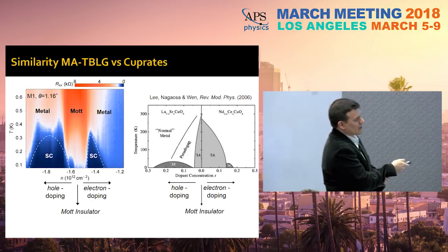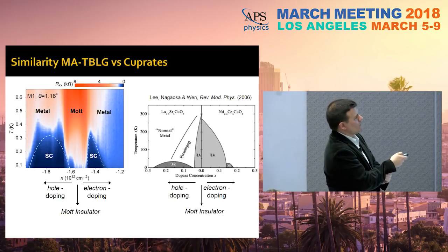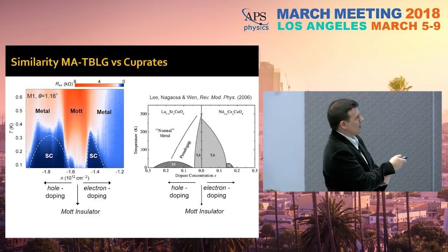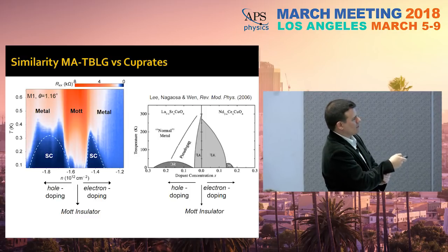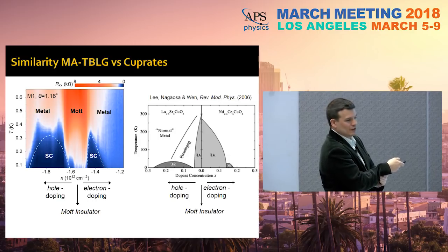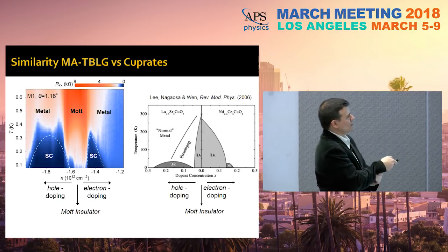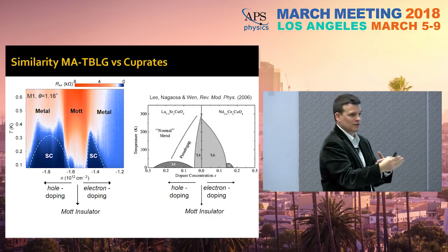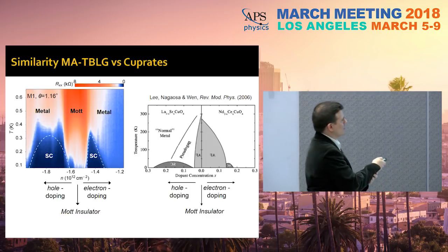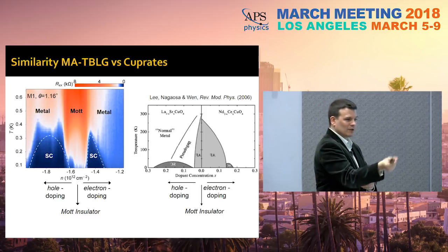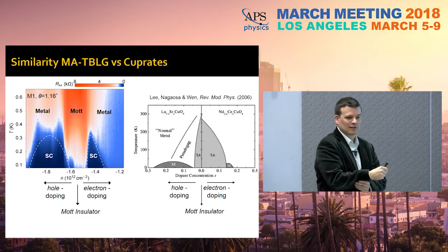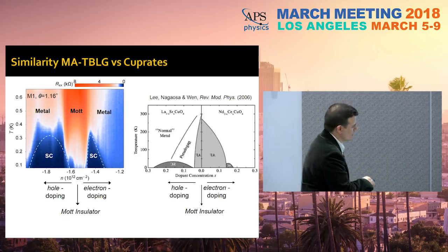But in order to do this in the cuprates, you need, first of all, different material classes for electrons and for holes. And second, to fill this entire gap, this is always a theoretical phase diagram. Experimentally, you need a different crystal, a different growth for each point on this axis. So in order to do this in the cuprates, you need actually hundreds of crystals and hundreds of materials. And we're able to do this electrically because we have electrical control of our density.